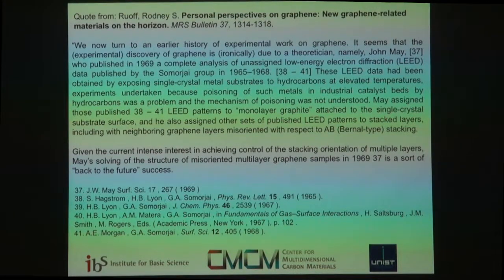Why didn't the industrial researchers understand what was happening? That the small nickel and palladium and other particles were being coated by something like a fullerene shell, because they didn't have the sorts of experimental techniques we have now. They might have guessed that, but they didn't really have a way of discerning a monolayer of sp2 bonded carbon completely coating the metal particle to completely poison the catalysis.